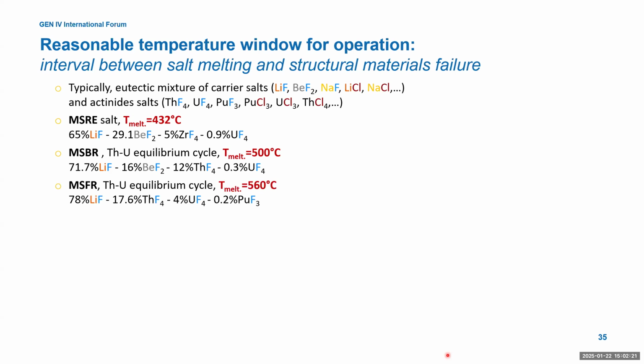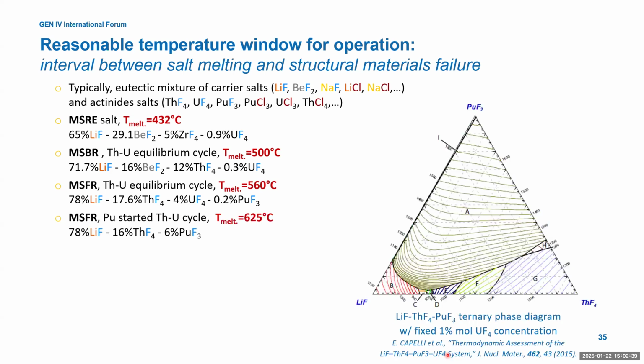MSFR is foreseen to operate in the thorium-uranium fuel cycle, and it has a fast spectrum. So the beryllium was removed from the salt, and the melting temperature again increased by 60 degrees C to 560. If you would like to start this reactor just with plutonium, your melting temperature would be in the sky. Consider that the structural materials probably can be operated up to 700, 750 degrees C.